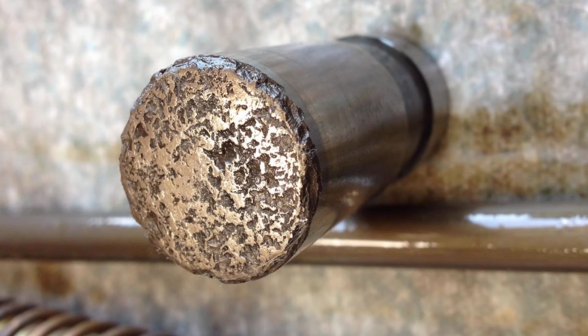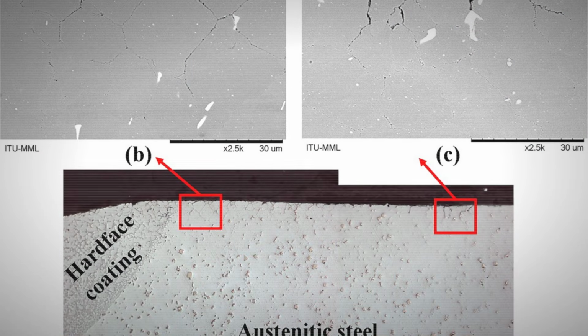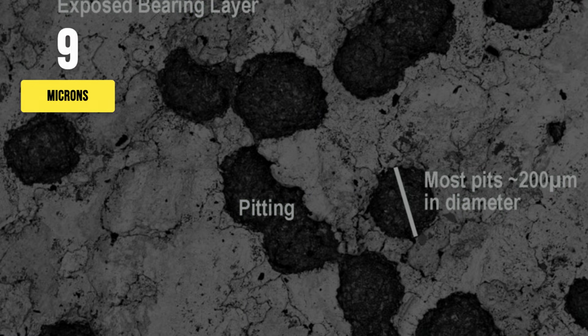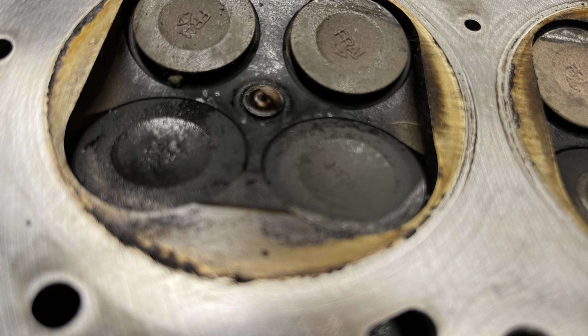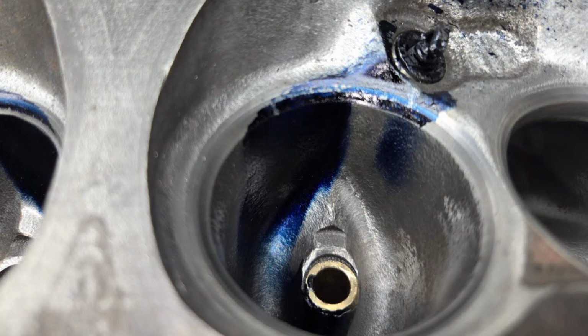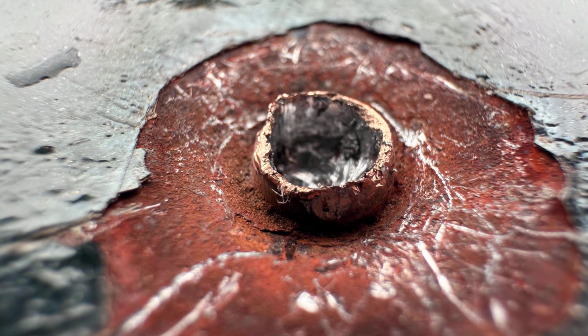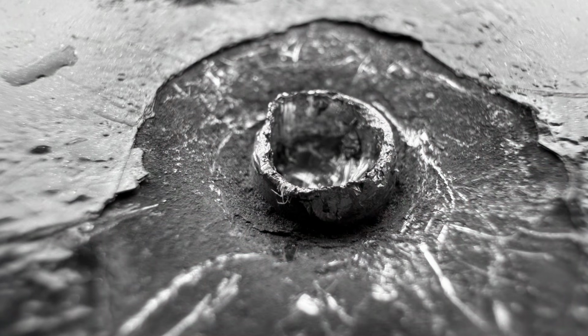A bench test cylinder sits open, its exhaust valve face pocked with craters that run from the margin to the center. Under magnification, the story is clinical. Pits start small, 10 microns across, barely visible to the naked eye. But cycle after cycle, those pits grow, connecting, deepening, gouging the contact band until the seat itself is chewed away. The surface that once gleamed like polished chrome now looks like the moon, scarred, uneven, and doomed.